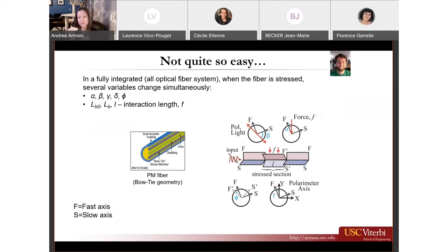And then when you begin to stress the fiber, you end up with a stressed section of the fiber over the area that you're compressing. That stressed section will experience a polarization change. Depending on the length of the stressed section and the amount of pressure it experiences, that will determine the magnitude of that polarization change. Since we know the magnitude of force we're applying, because that's a known variable, and we know the length over which we're applying it, we can then back out the change that's being induced.